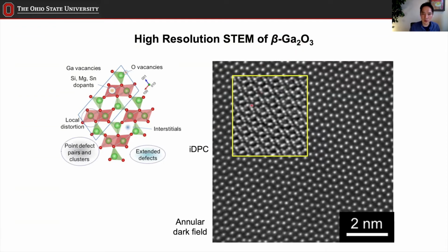But you can also use some other modes to be able to detect the oxygen positions. One example is something we call the integrated differential phase contrast mode, and you can see the oxygen atom positions are also showing up. That's great, because now we can compare what we know about the structure and what we see here. If you compare these two to each other, there's a perfect match. That's great. So we can get all these atomic scale details, and this confirms that.